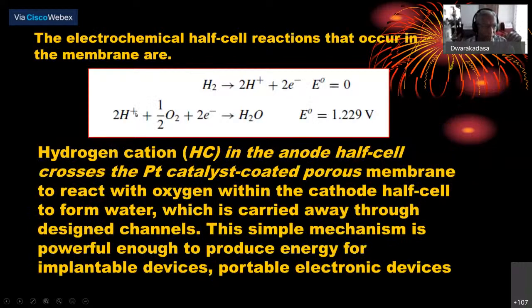The electrochemical reaction in the fuel cell is simply burning hydrogen, with hydrogen and oxygen combining to form water and giving a voltage of 1.229 volts. The hydrogen cation in the anode half cell crosses the platinum catalyst coated porous membrane. Please note that we need a certain catalyst, and the catalyst almost controls the whole system. It reacts with the oxygen within the cathode half cell to form water, which is carried away. This simple mechanism is powerful enough to produce energy for implantable devices and portable electronic devices. Although we say we use fuel cells in a large way, unlike batteries.